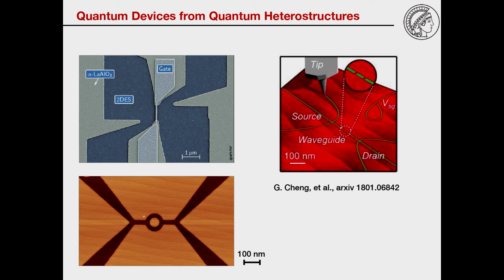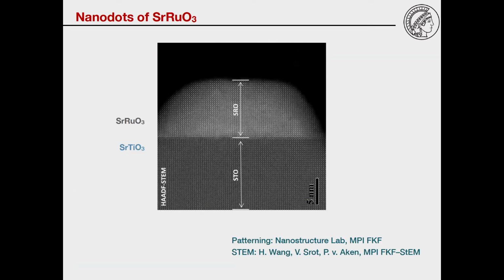We have learned, with advances in growth techniques, to grow many, many different compounds with atomic layer precision. This is just a small sketch of atomically controlled heterostructures that have been made with complex oxides, for example, and related compounds. Now, the next step is to use these materials and pattern them also laterally into quantum structures, which is possible by a variety of techniques, and several groups are working on this. The most advanced one is Jeremy Levy's group. They have this fancy STM writing technique, with which for some materials they achieve a resolution of very few nanometers. We are doing similar things with e-beam lithography, where we can fabricate quantum devices, for example, for transport, or also quantum dots, with a resolution of about 20 nanometers. And this is really exciting, and I think it opens up many perspectives.